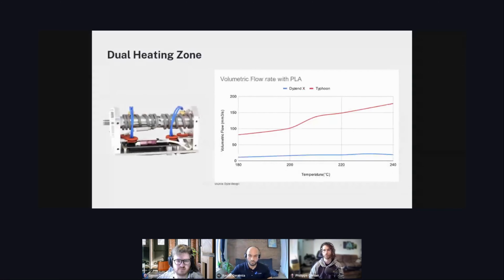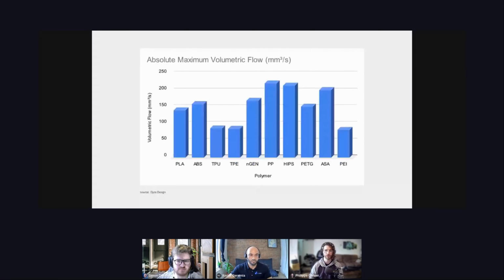If we compare the Typhoon to a standard hot end like our Dyze X, we see about 6 to 10 times faster flow. Both extrusion systems are using the biggest nozzle available to them. We can also see that the Typhoon throughput scales much better with the temperature, thanks to the dual heating and longer melting zone. We advertise the Typhoon as 200 cubic millimeters per second, but that's an average flow rate because, as you can see here, the Typhoon can reach a bit more or less depending on the specific material you're printing. The amount of heat required to melt, the viscosity, the added fillers, and the coefficient of friction are parameters that affect the maximum output flow.